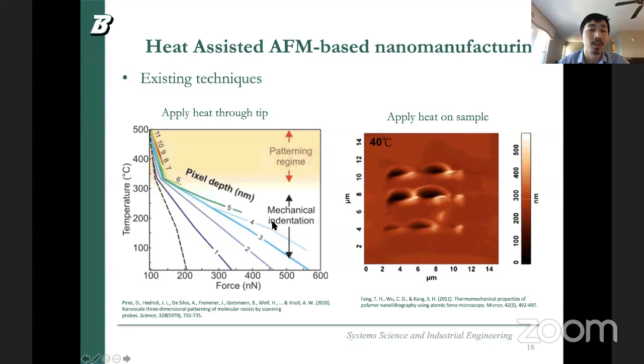So it's not only indentation, because there are two regions. The upper region is the patterning, which means higher temperature and from 100 nanonewton to about 600 nanonewton to get patterns. If you don't need consecutive patterns and only need indentation, like the IBM Millipede project fabricating memories, it doesn't need that high a temperature, but it still needs that high force. This paper was published in Science 2010, showing a very promising technique using heat to do AFM-based nanomachining.